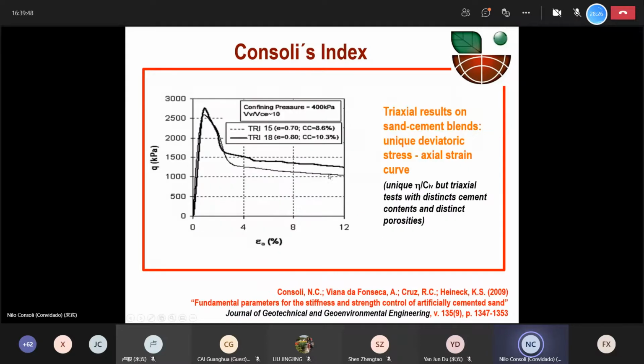Here we got a case in which this relation between porosity and volumetric cement content was 10, for example, and we molded specimens with the same index, but different void ratios and different amounts of cement. After carrying out triaxial testing, in this case for a confining pressure of 400 kPa, we realized that the stress-strain results were the same. As I said, one specimen was molded with 0.7 void ratio and 8.6% of cement, and the other with 0.8 void ratio and 10.3% of cement.